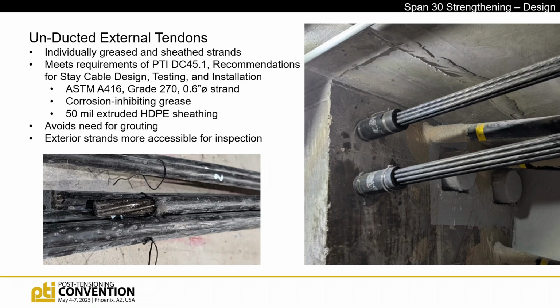But it provides the same level of corrosion protection, maybe a little bit improved over a grouted condition. Interesting note, which we learned only about a month and a half ago: this is, we believe, the first application of an unducted tendon system in a bridge superstructure in the United States. The second one was the Laurel Fork Bridge, done about 6 or 8 weeks ago. I think they finished that one up, and they chose to use epoxy-filled and coated strands. Interestingly enough, Structural Technologies was the contractor for both of those, and they could talk to you about the two different approaches for the unducted tendons.